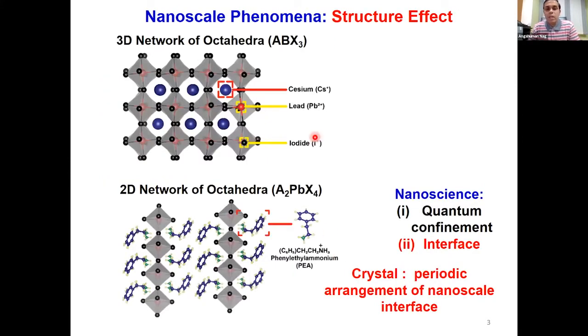Now here what I'll try to say is that we can perhaps see some of this nanoscale phenomena even in bulk crystals, provided they have the right kind of crystal structures. So this is the three-dimensional perovskite structure, the famous ABX3 perovskite structure. For example, this is for the cesium lead iodide perovskite structure. You can see that these are the lead iodide layers which are connected in all 3 dimensions, and the voids that are created are occupied by the A-site cation, which is the cesium plus.